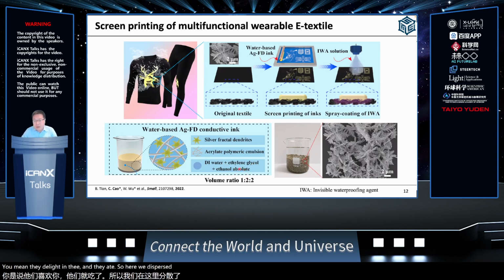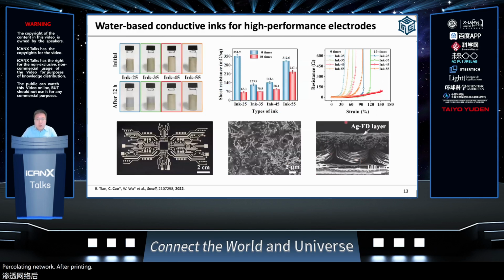Here the conductive silver ink has a hierarchical structure, so it can form a percolation network after printing. With the same conductive filler percentage, we adjusted the binder ratio and got different inks. We found that inks 45 and 55 can stay stable for a long time and be used for quality printing work. We also found that ink 45 has a low resistance, so we selected this ink. With it, we can print high-resolution, nice circuitry, and in the top surface and cross-section SEM images, we can see the percolation network formed by the silver fractal dendrite.